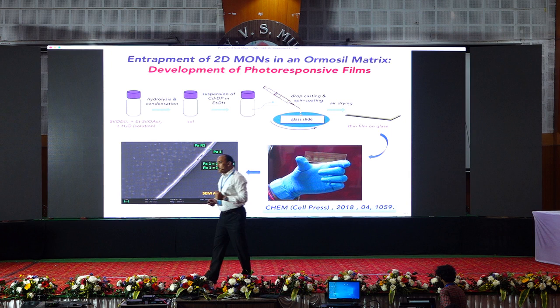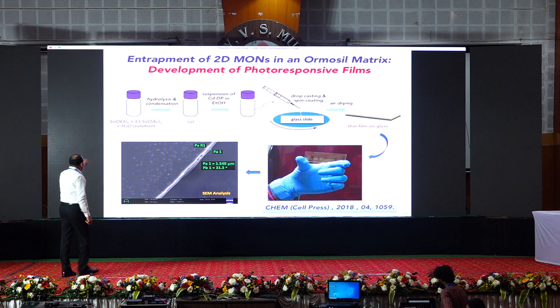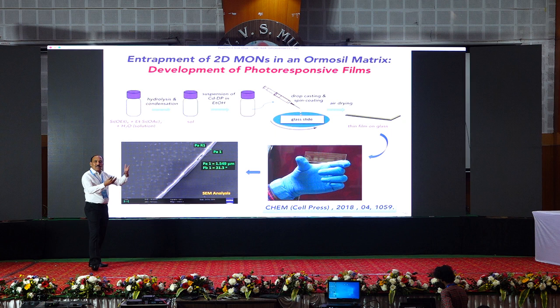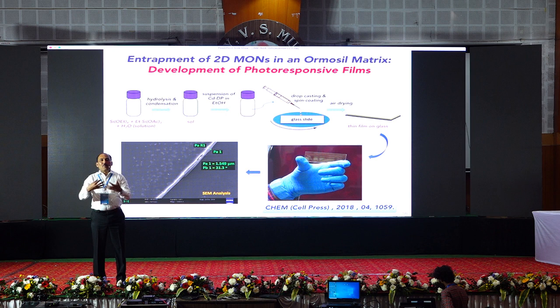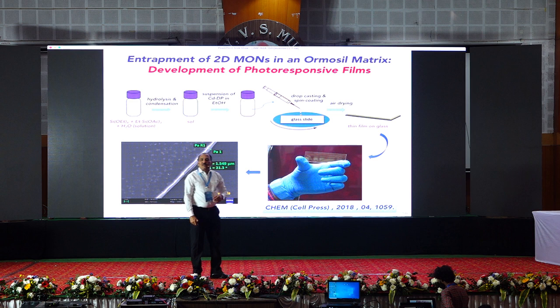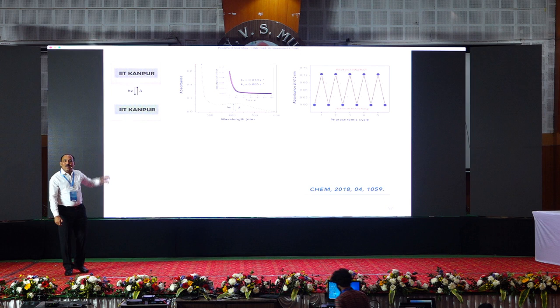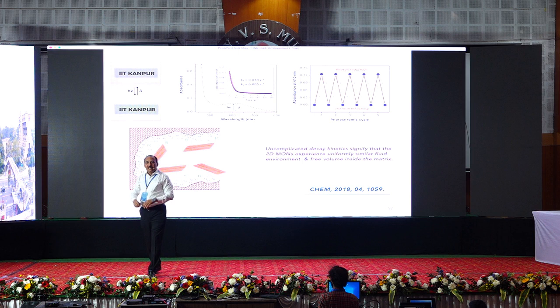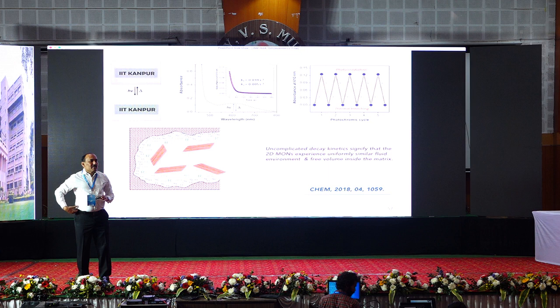Now, I don't want to show it with PMMA, but there is something called organically modified silica gel, and I take this kind of triethoxysilane and ethyl triethoxysilane, and by hydrolysis, you can make a sol. In the sol state, you put in this 2D material dispersion. Now the polymer-polymer intermixing happens, and of course, you can coat it on a slide, and do you elicit this property on the slide? And here it is. The compound is supposed to be pale yellow. Shine light, it becomes green and goes back. And you can oscillate between the colors multiple times. This is from molecules to materials, of how you create 2D materials that respond to your call.